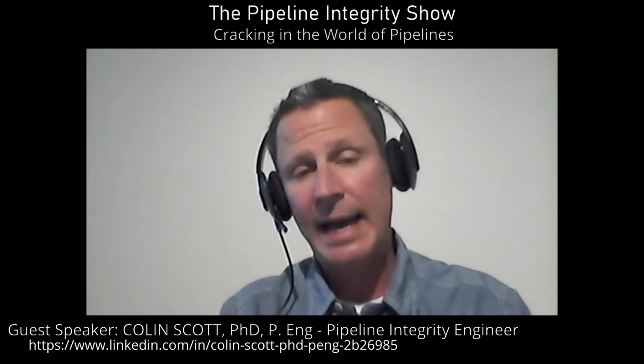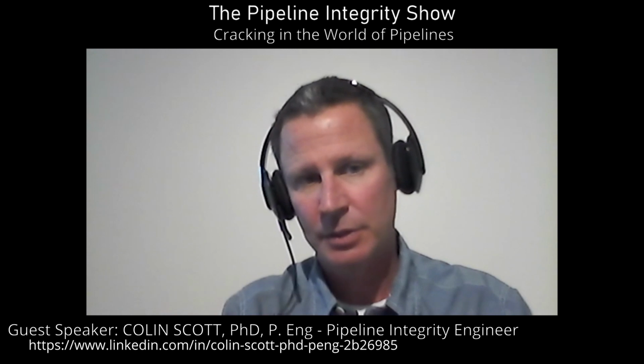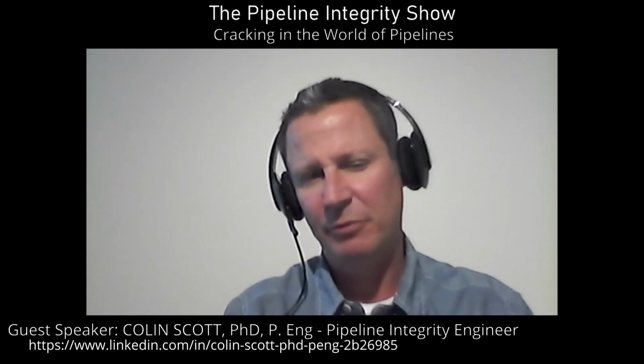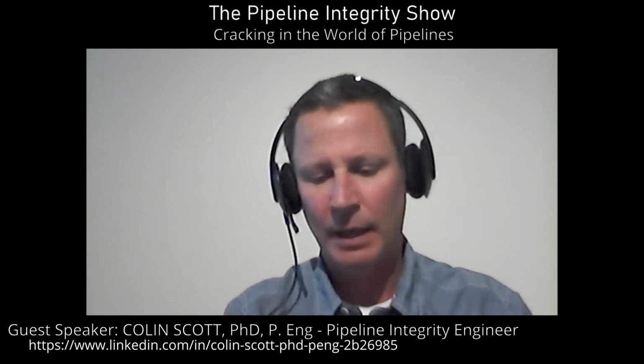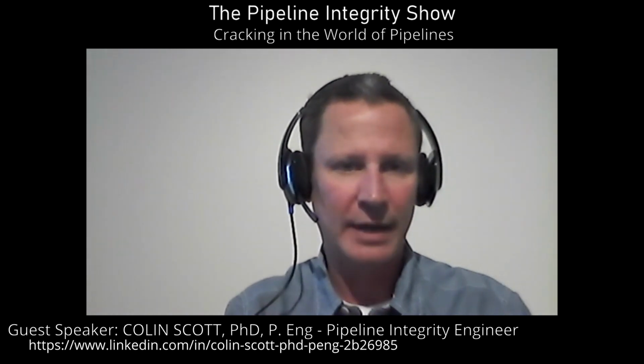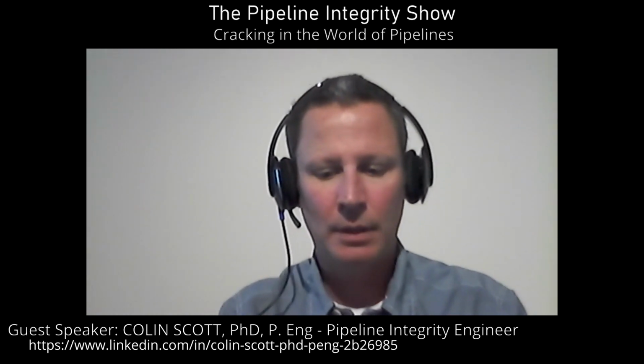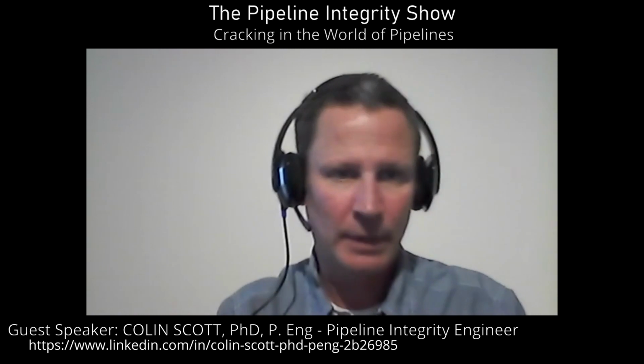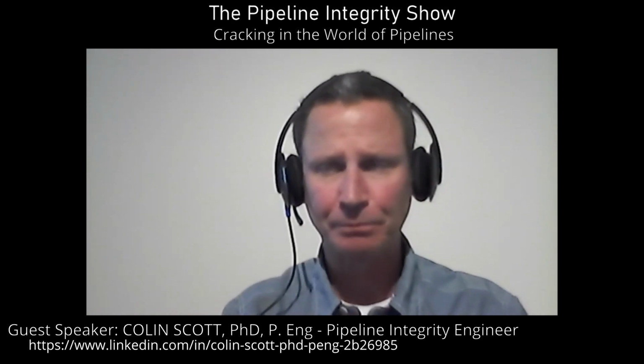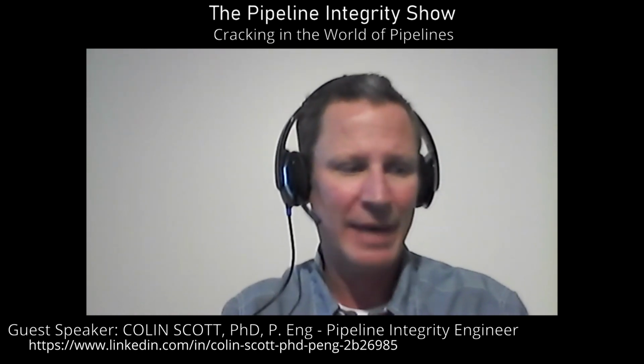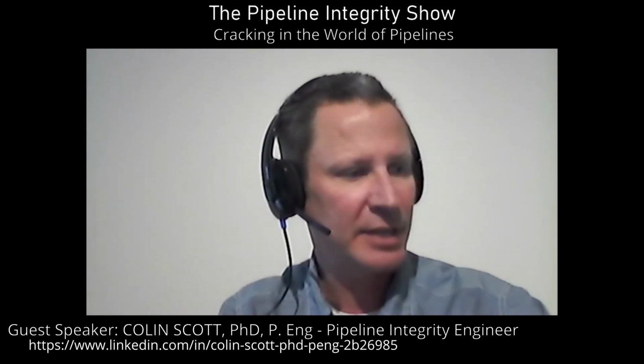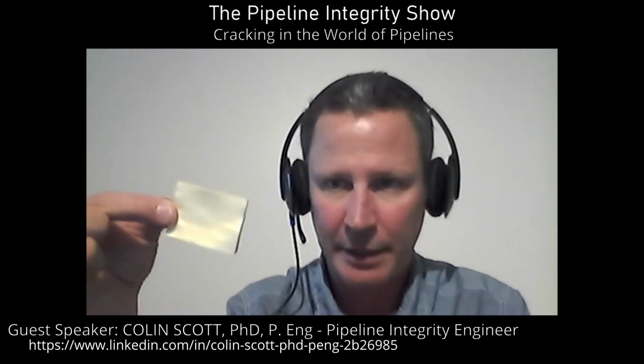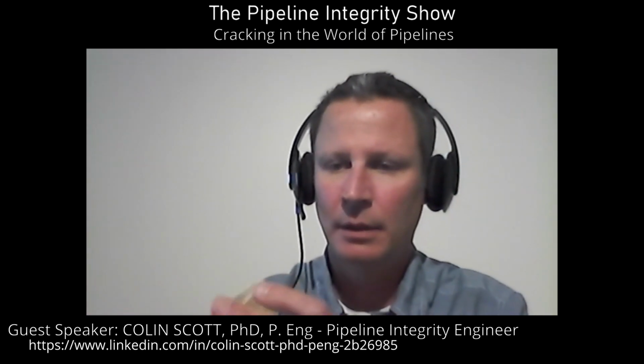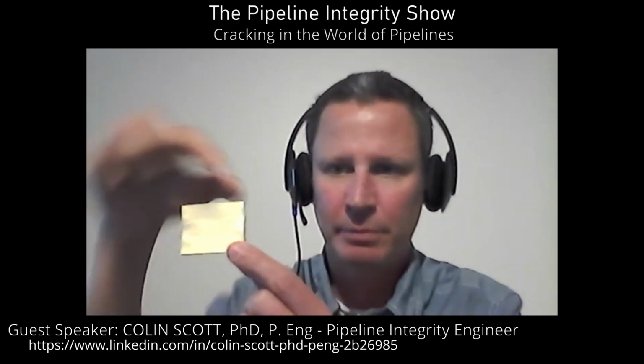But in the academic world of fracture mechanics, it doesn't quite fit with anything else that's being done. If you look at the academic world of fracture mechanics, you'll see K1C toughness tests, and those are typically done with what's called a compact tension specimen. A compact tension specimen is probably about the size of my little sticky pad. You put a crack into it, and then you basically, why don't I do that?